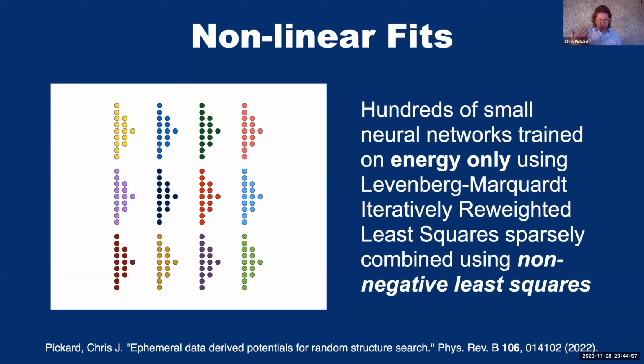And then one of the key features is that we do this multiple times, and we combine the results of multiple neural networks together in a linear combination. So we take the result of one neural network with another neural network with another neural network, all added together with parameters, and we adjust those parameters so as to minimize an error on a held out validation set, but we put a constraint that the parameters that we use are always positive. And that's known as non-negative least squares, and it results in sparsity. If you put that constraint, your parameters are either small and positive or zero. And so the neural networks that develop a zero parameter in front of them can just be thrown away. We don't need them anymore. So it sparsifies the data.